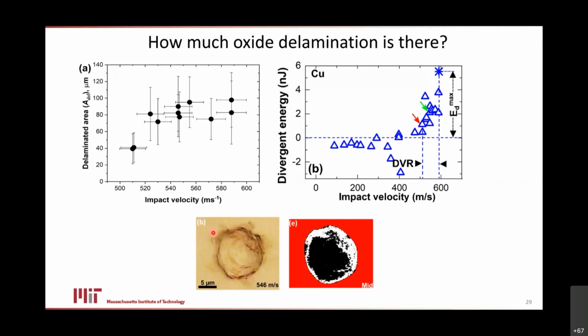And so here's a whole bunch of data for a bunch of shots that we've done. All of these lie in that divergent regime where jetting has set on and bonding is about to happen. And we're pretty convinced now that we're delaminating oxides first at the rate of maybe a few dozen square micrometers, and ultimately as high as perhaps 100 square micrometers of delaminated oxide.